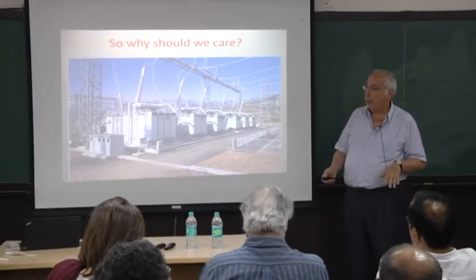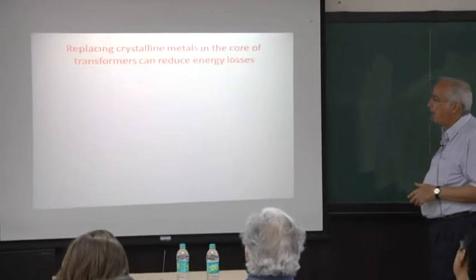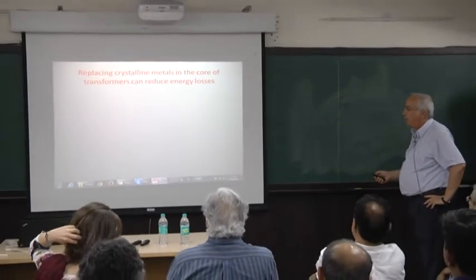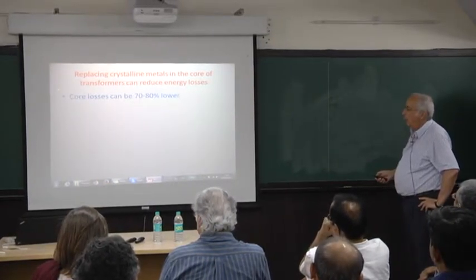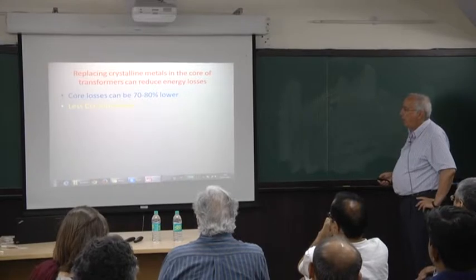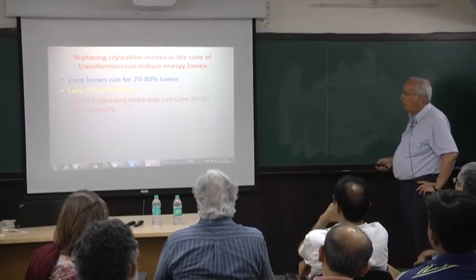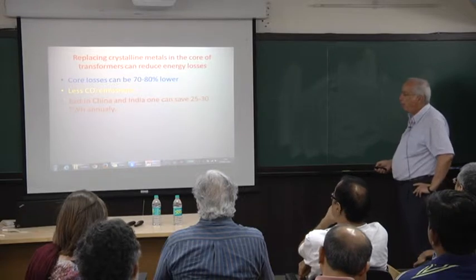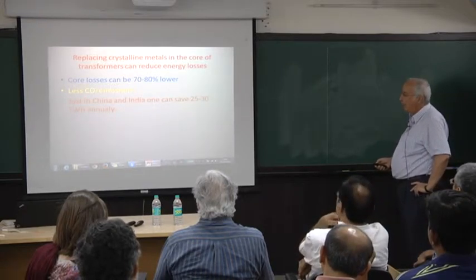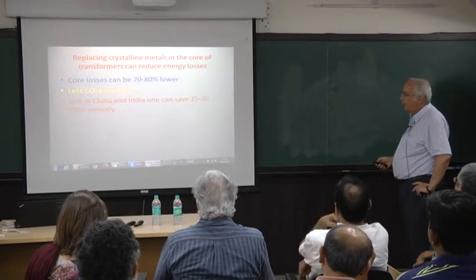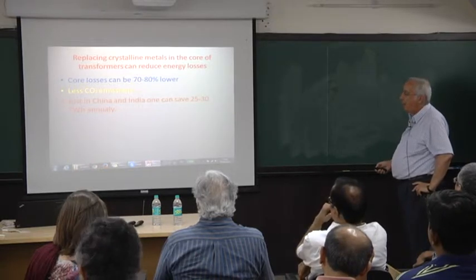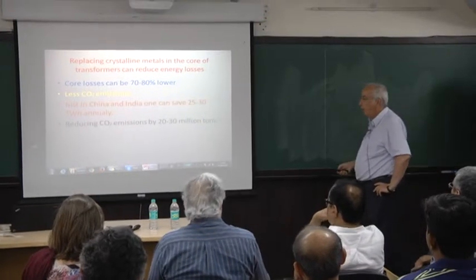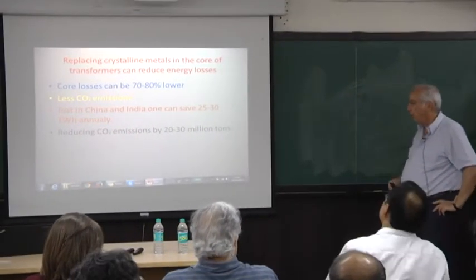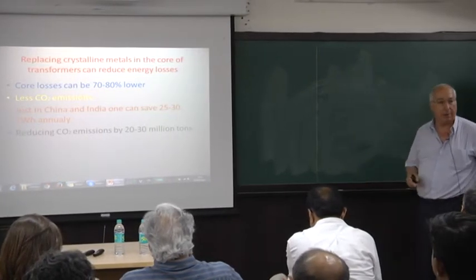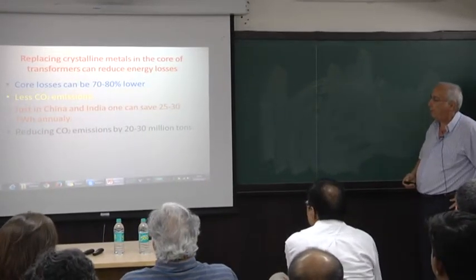If you compute what you could save, if you replace the crystalline metal in the core of transformers with metallic glasses, core losses can be 70 to 80% lower, with less CO2 emissions. I did a back of an envelope calculation for China and India, and I concluded that you could save about 25 to 30 terawatt hours annually. This would be a reduction of CO2 emission by 20 to 30 million tons. It's significant. Something that one may want to have.